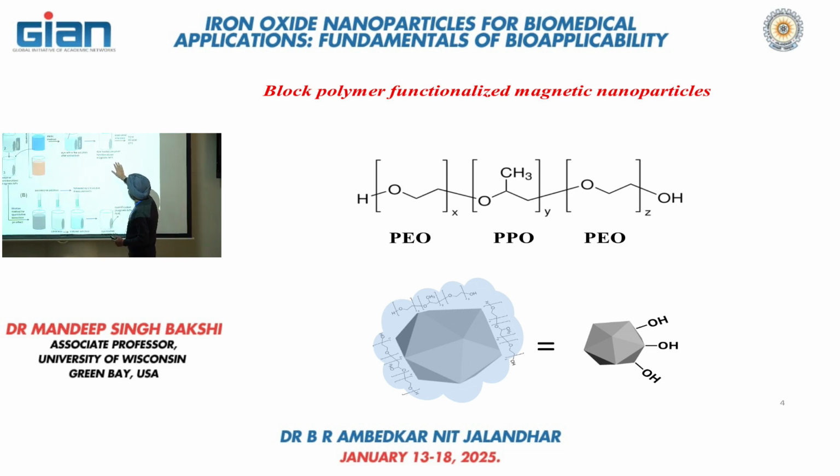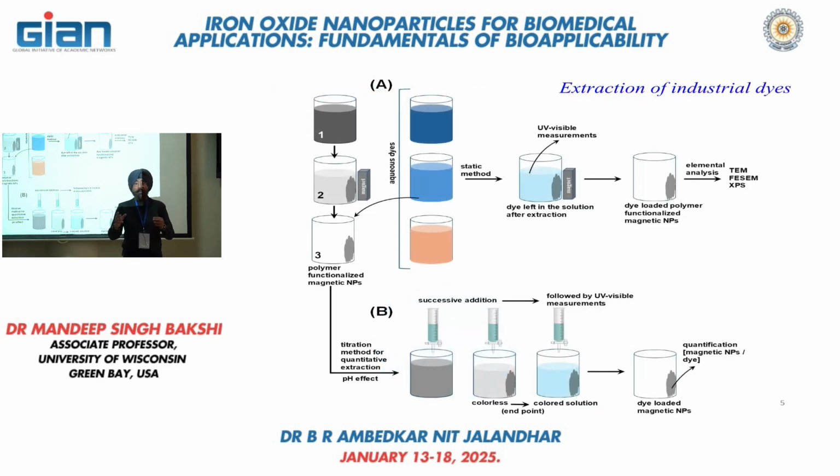Apart from that, I can calculate how much amount of the dye has been extracted by taking how much amount of the magnetic nanoparticle. And suppose you may ask me, how long you have to keep it in the dye solution? We have performed the experiment and we have seen that some of the dyes are extracted within just few minutes and the solution you are going to get is transparent, but some of the dyes take a very prolonged time. It means that overnight or maybe 3 to 4 days eventually when you get the clear solution.